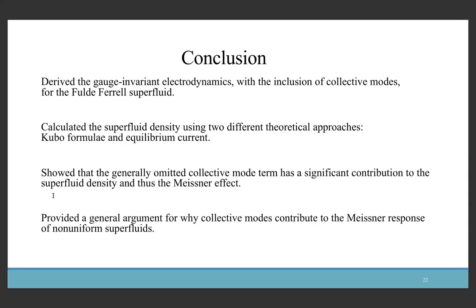So the typical way that you do this is you're looking at the superfluid density. So experimentally you tune the temperature and then you measure the resistivity, and that's how you do this. But based on either the thickness of the ferromagnet or the thickness of the superconductor, you can see highly non-trivial behavior in the critical temperature for these systems. Right. Yes. I mean, in principle, yes, the TC would be significantly reduced for the Fulde-Ferrell phase in comparison to a conventional superconductor.